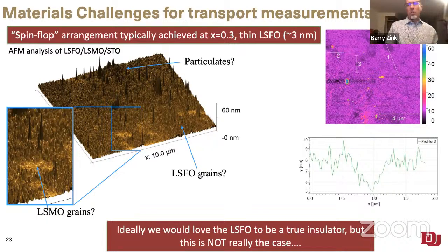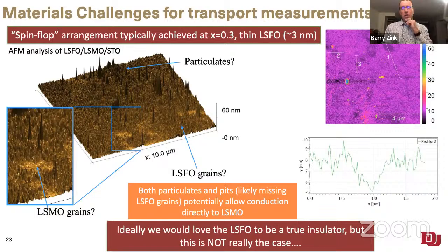So already at the fairly beginning of this process, I was thinking, probably naively, of the LSFO as just an insulator, and the LSMO as this conductor underneath it. Well, you realize that if you put some layer of platinum on top of this thing, your chances are good you're going to encounter one of these missing grains, and all of a sudden you're just putting charge into a ferromagnetic conductor, which brings all sorts of other types of side effects that are going to be difficult to sort out. And in fact, it turns out that's what we've been fighting for more or less ever since.